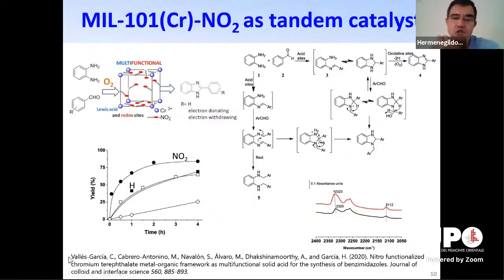Tandem reactions: one of the tandem reactions that we have studied is the formation of heterocycles, in this case benzimidazoles. The reaction starts with the condensation of the benzaldehyde with an amino group. You start with the amino, and the amino can evolve in different ways, and you may have byproducts, or you may have the final product. This depends on how fast the oxidation goes. So here we have acid sites, but we also need oxidation sites to obtain the final product, benzimidazole. And again, there is an influence of substituents on the aromatic ligand, and we understand that this is due to acidity. If you increase acidity, then you are also increasing the oxidation activity of the MOF.